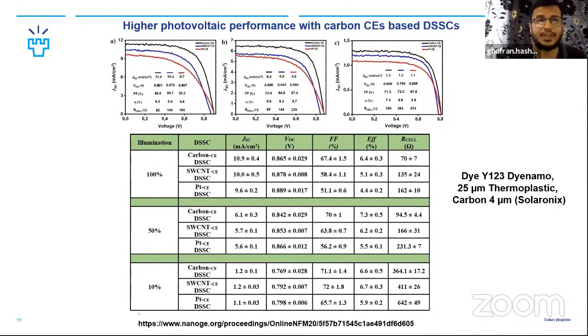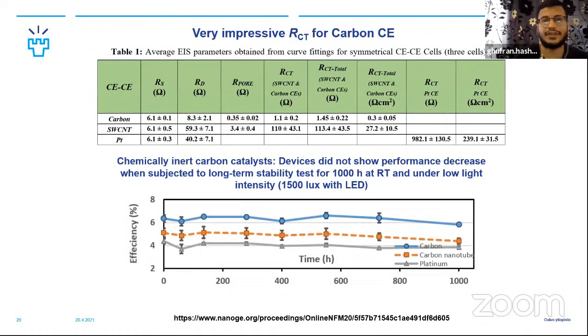So we again achieved very impressive performance compared to the single wall carbon nanotube based counter electrode and the traditional platinum, where this very low cost carbon paste, composed of carbon black and graphite nanoparticles, outperformed both the other existing catalyst layers in the presence of this copper electrolyte. The reason is that it provides a highly porous structure and more catalytic sites. So when we did the impedance spectroscopy again, it gave us a very low charge transfer resistance that influences the fill factor and also the open circuit voltage